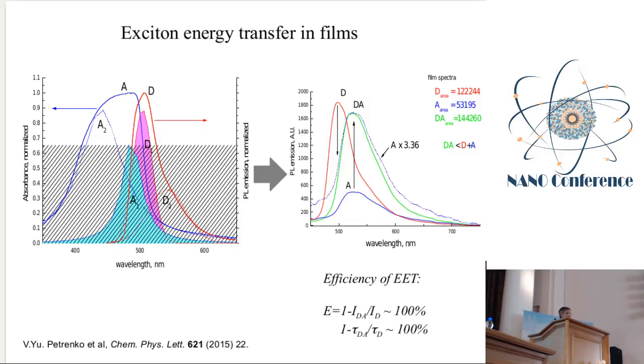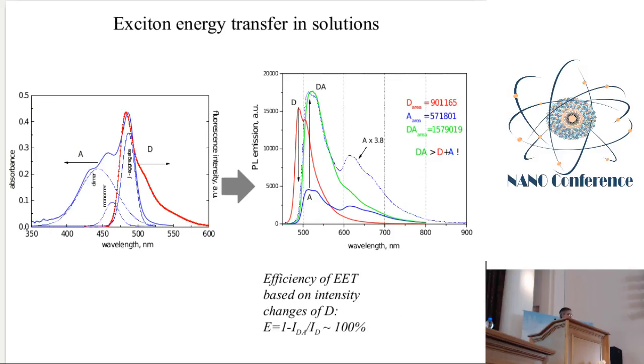In solutions, the situation is somewhat different. So again, we have a good overlap of the emission of the donor J aggregates and absorption of acceptor J aggregates here, which provides again a very high enhancement of photoluminescence of acceptor in the presence of the donor J aggregates. This enhancement is anomalously high because in terms of energy, if we calculate the area under the curves, we can find that the area under the green curve even exceeds the sum of areas under the blue and red curves.